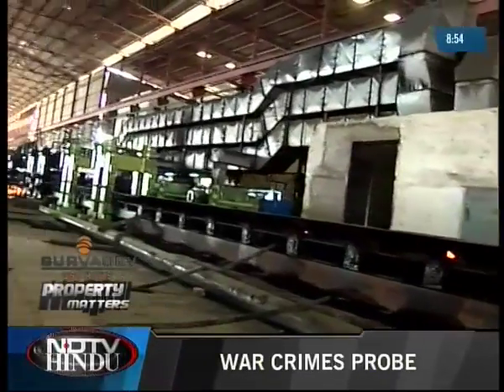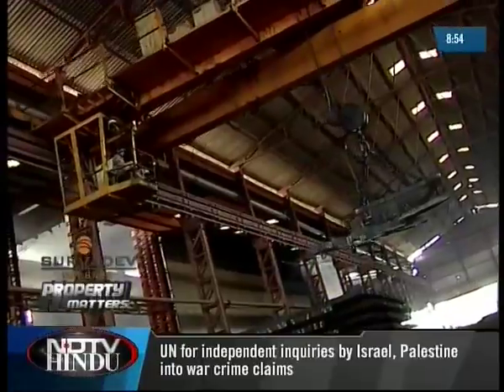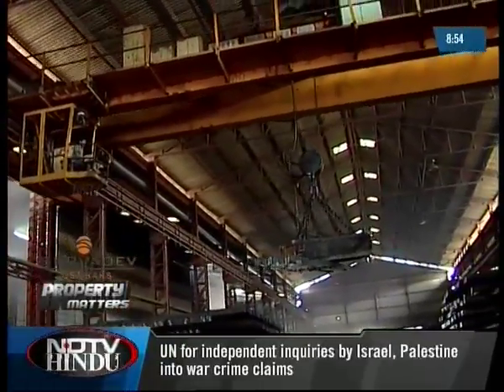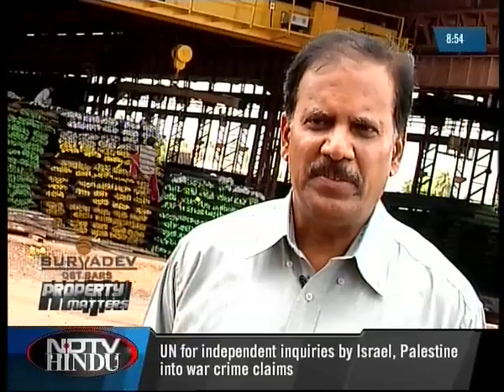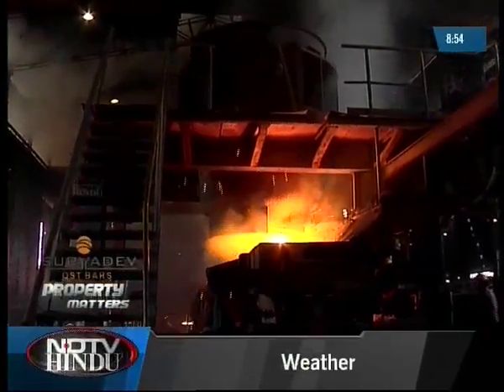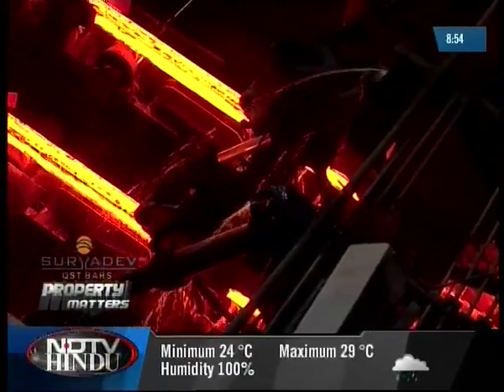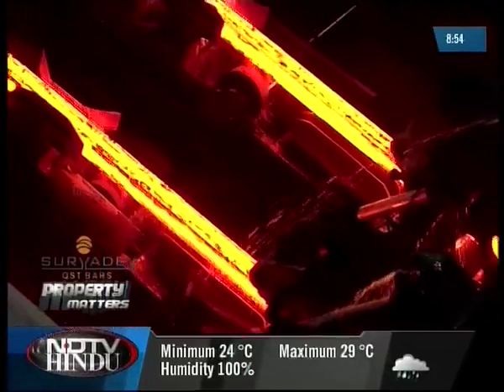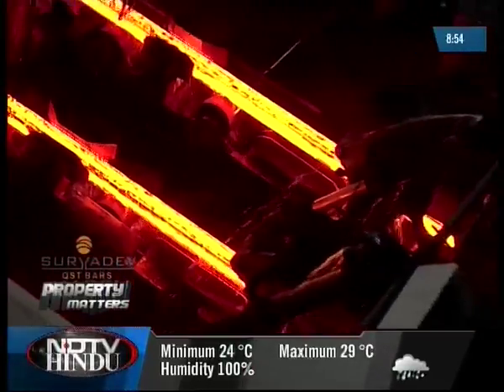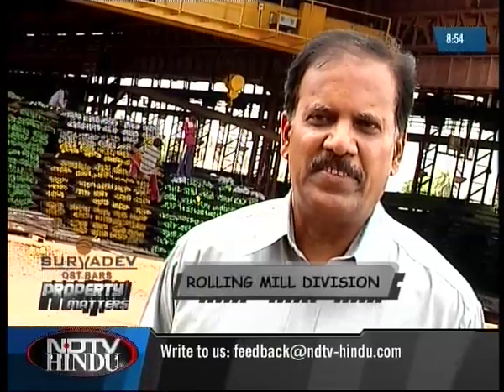Here at Suryadev's manufacturing unit in New Gummidipoondi, we took a look at the conversion of this metal from virgin steel to finished bars. To start with, melting takes place in electric induction furnaces, where the molten metal is taken in a ladle to a continuous casting machine, where it is cast into different sizes of billets. These billets are taken for reheating in a billet reheating furnace, where the temperature is raised up to about 1150 degrees centigrade for plastic deformation.